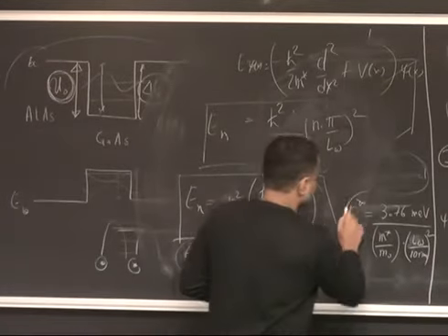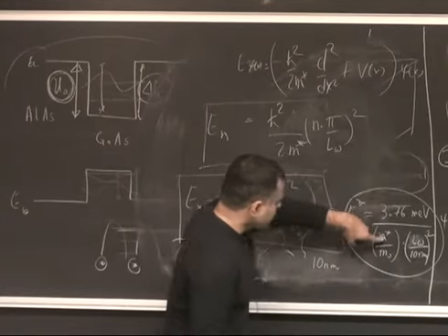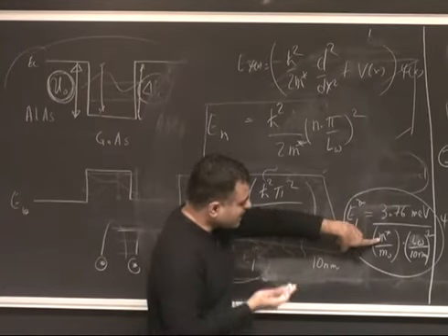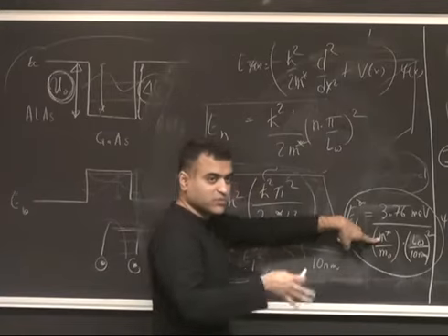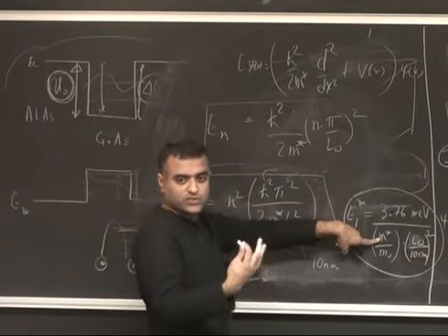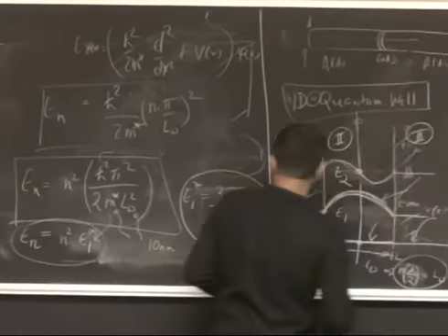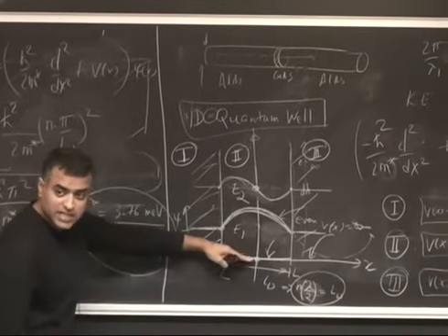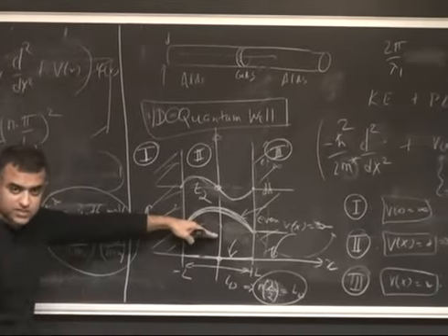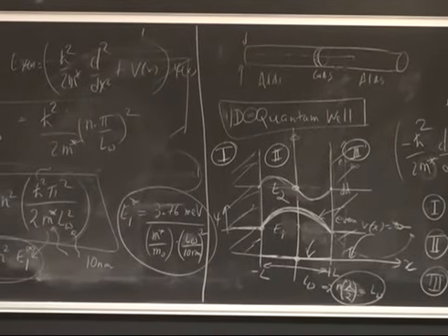What does this mean? If my effective mass in that band is 1, it's like a free electron. That's very heavy, actually. In most semiconductors, it's like 0.01, 0.1, and all that. And the quantum well width is 10 nanometers. Then the ground state is 3.76 milli electron volts above 0. That's what it means. 3.76 meV, not electron volts, milli-electron volts.